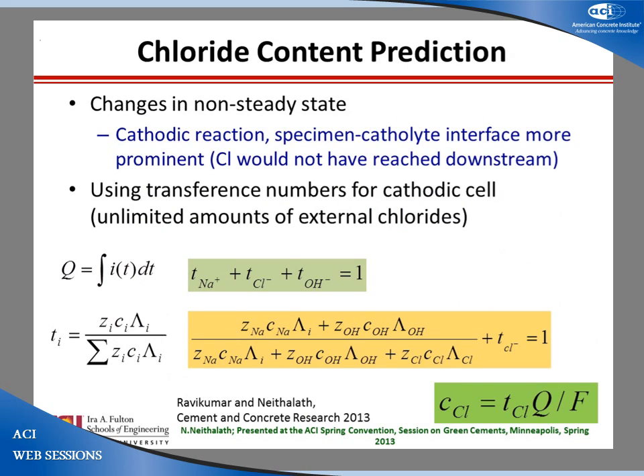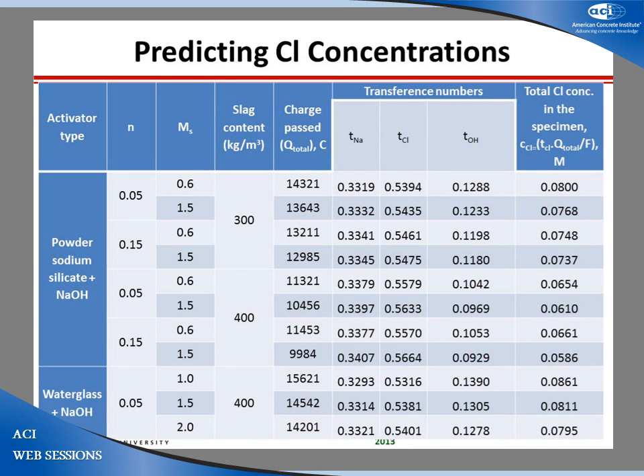A quick way to predict the chloride content, and this is applicable to all types of concretes, is based on transference numbers. We are basically using the total charge passed as an integration of the current over time, and then you're essentially saying that, okay, I have non-steady state migration, which means I don't have chlorides in my anolyte cell, which means all the chlorides are either in the catholyte or in the specimen, and I can say that whatever is in the specimen is much lower compared to whatever is in the catholyte because I have a very high concentration of chlorides in the catholyte. So you can actually look at equating the transference numbers. You can do some simple operational procedures to do that and get the chloride concentration as transference number of chlorides times Q over F. F is the Faraday number, and a list of other things that you look at.